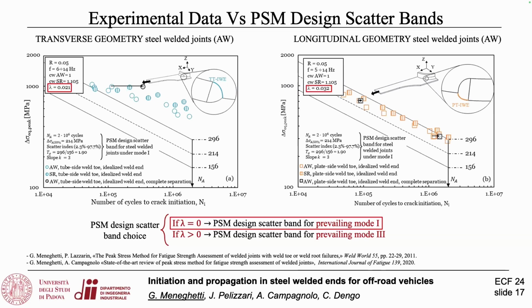You see the fatigue life and the equivalent peak stress. This is not fitted on the experimental results. This is a validation. So this is a pre-existing design curve. If correlation were perfect, the experimental data points should lie on the 50% survival probability line. We are not exactly there, but we are inside the scatter band. We are very much on the safe side instead for the transverse geometry, and we wanted to investigate this a little bit, because after processing more than 1,000 experimental results, this situation was quite new for us.